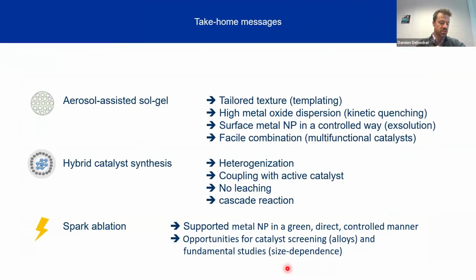So this brings me to the conclusion of my talk. I hope I could illustrate that the aerosol-assisted sol-gel process offers many opportunities to tailor the texture of your materials, to target high metal oxide dispersion in your silica, but it could be another oxide, via what I call kinetic quenching. If you need nanoparticles, you can start with a material where the metal is trapped in the oxide, and then you trigger the exsolution of the nanoparticles by calcination. And you can easily combine and have multifunctional catalysts that are very interesting for a range of applications.